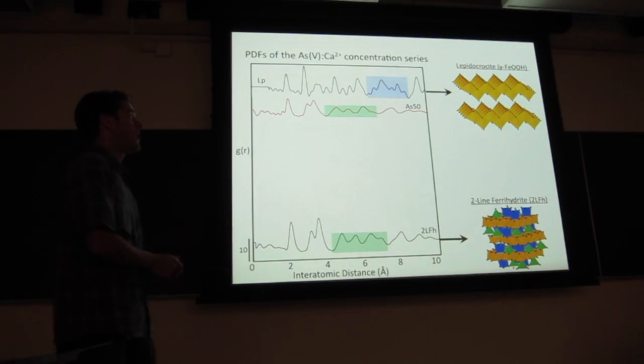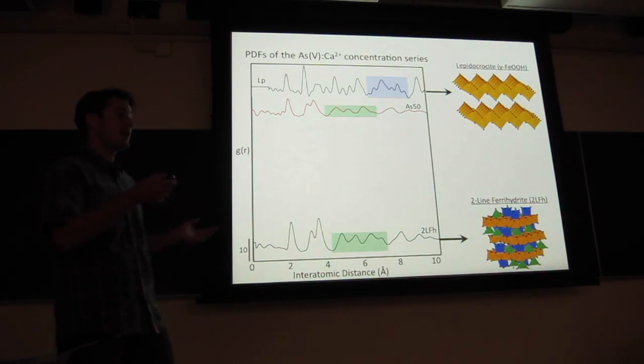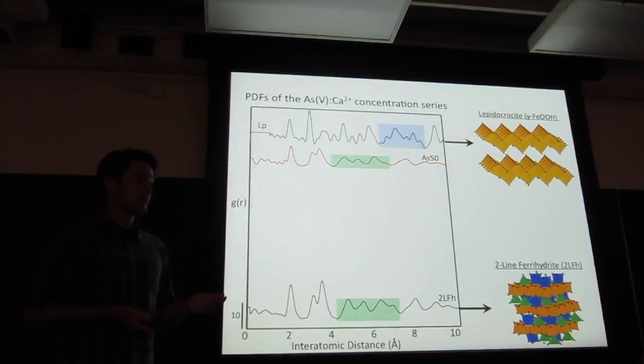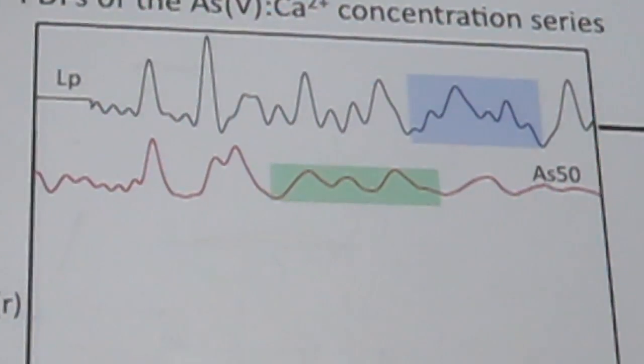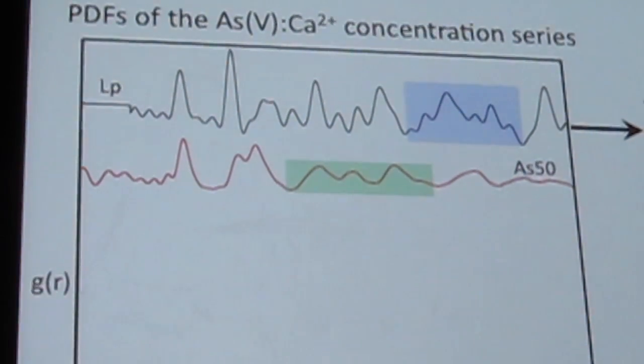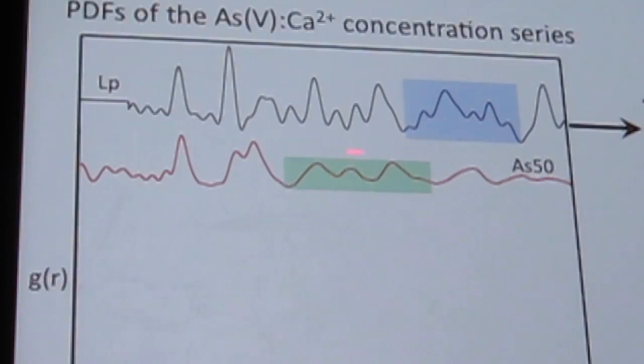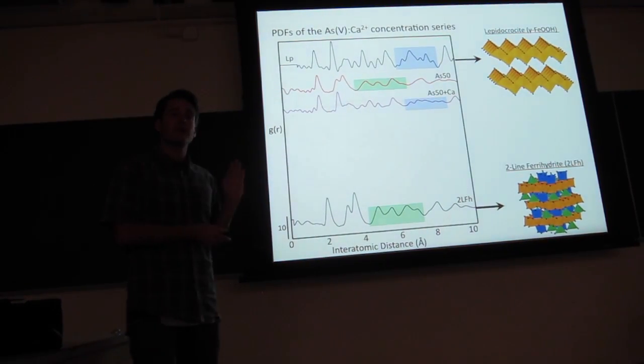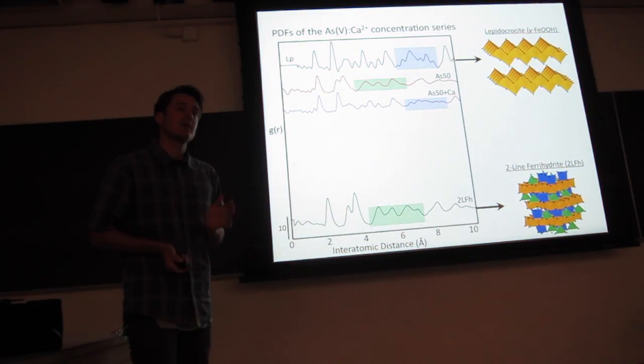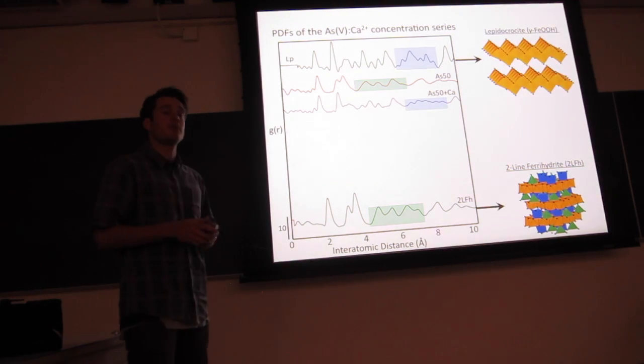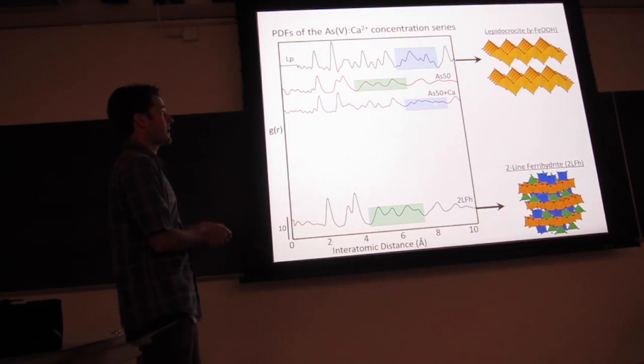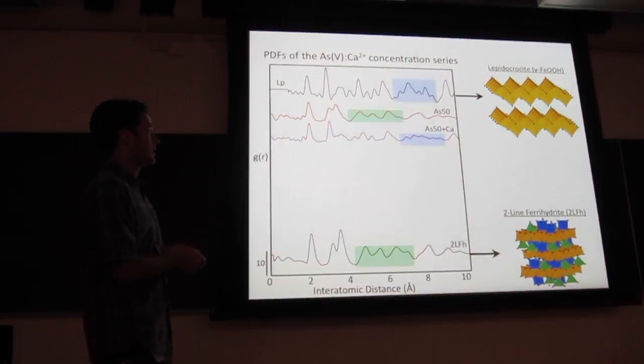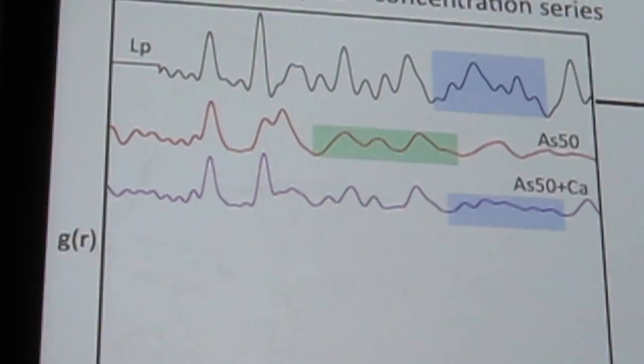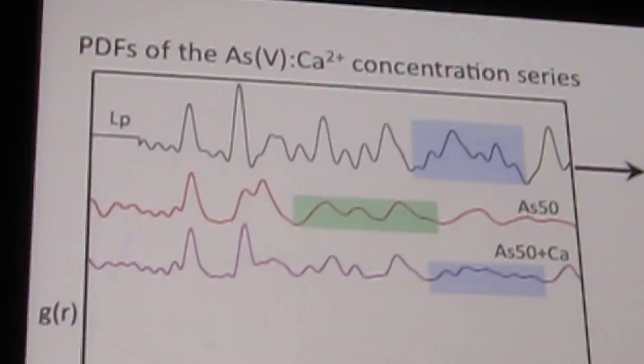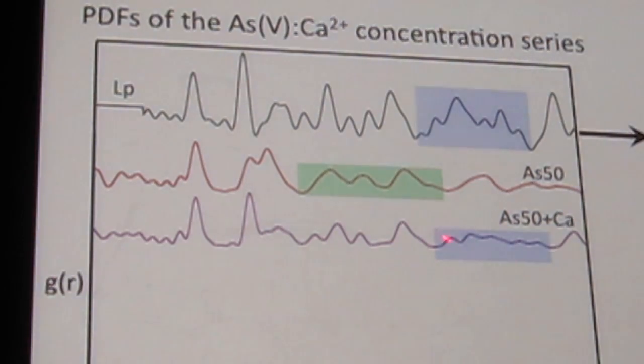So at the lowest initial arsenic concentration, 50 micromolar, you get something that looks like ferrihydrite again, and here's the green thing. The arsenic was depleted 4 minutes into electrolysis, and you had the majority of iron being generated in an electrolyte with no aqueous arsenic. And so that's why we see lepidocrocite here. This is actually multi-phase, which we saw from the TEM images, but the PDF probes the average structure, and so that's why we see this lepidocrocite line shape again.